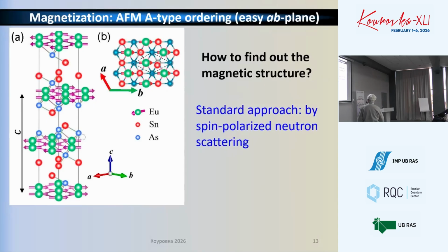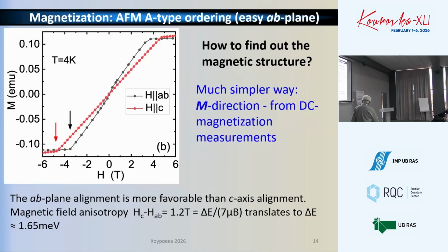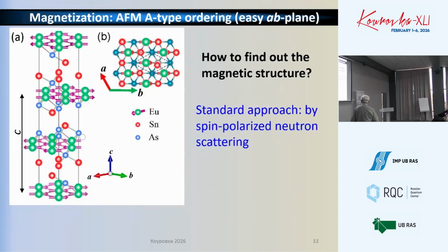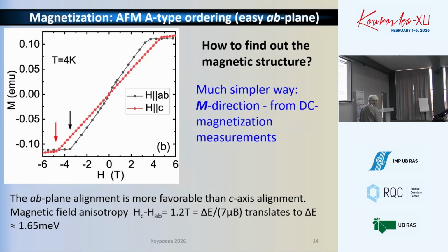Just for the beginning, from the lattice structure, you see that the smallest distance between europium atoms is in plane, and therefore the order is in plane. And the question is how the interplane ordering sets in, and, as issue number one, how the magnetic moments are arranged in space, and the second issue is who is actually responsible for the magnetic ordering. The standard way is to go to Brookhaven or other laboratories where there is spin polarized neutron scattering, and it is of course a standard approach, but not necessarily it gives the complete answer. But actually, applying common sense arguments and doing very simple measurements like magnetization, you can immediately understand the magnetic structure.